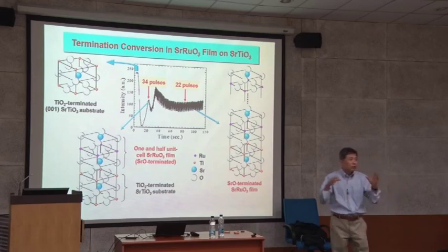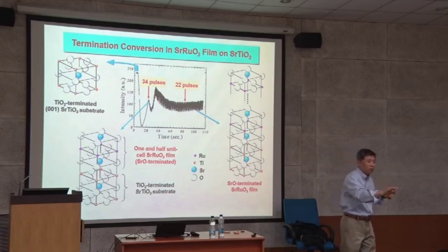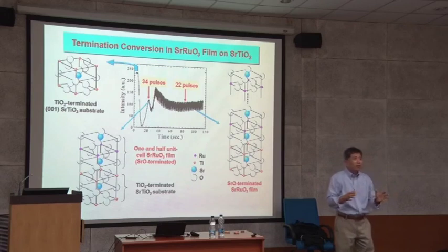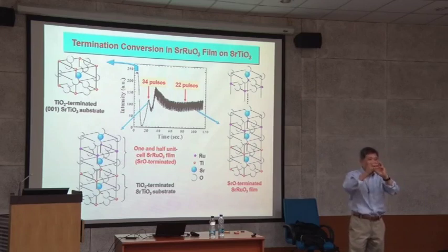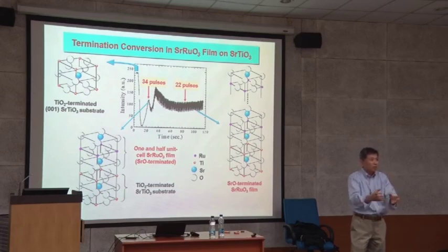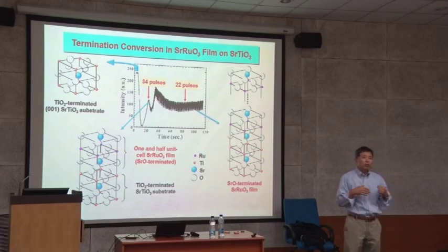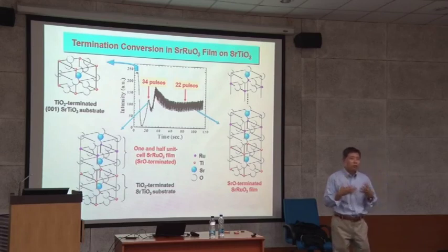You understand? So when strontium titanate grows, the strontium atom comes down and finds the strontium position, and then it still has to be oxidized. Oxygen comes in and goes there, that's the best way. But if you form gas-phase strontium titanate, it's already crystallized and doesn't like to be stuck there. So the rule of thumb is, when you grow oxide at a high oxygen partial pressure, in general you have to increase the temperature.